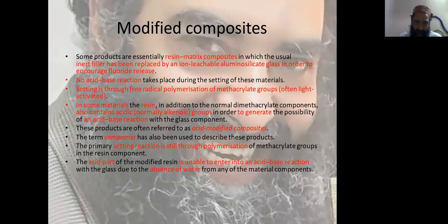The acid part of the modified resin is unable to enter into an acid-base reaction with the glass due to the absence of water, as no component of this material has water.